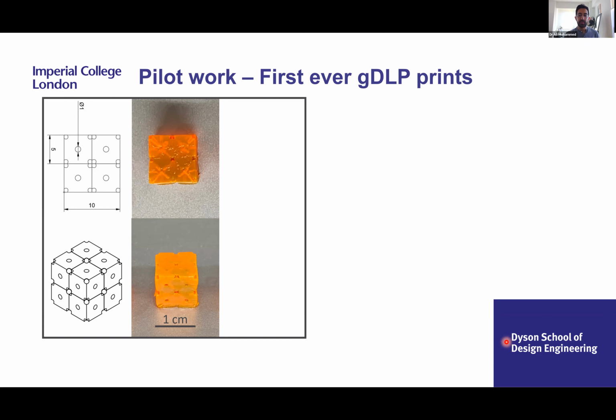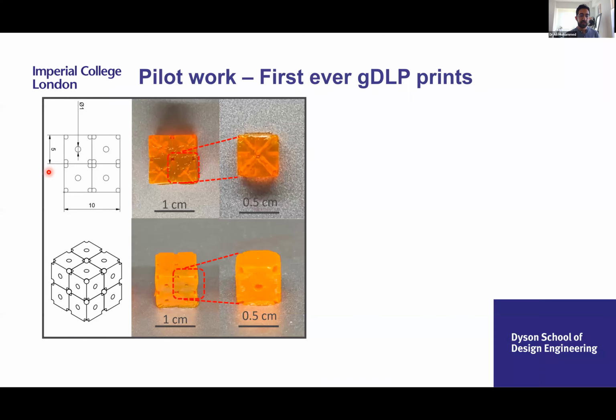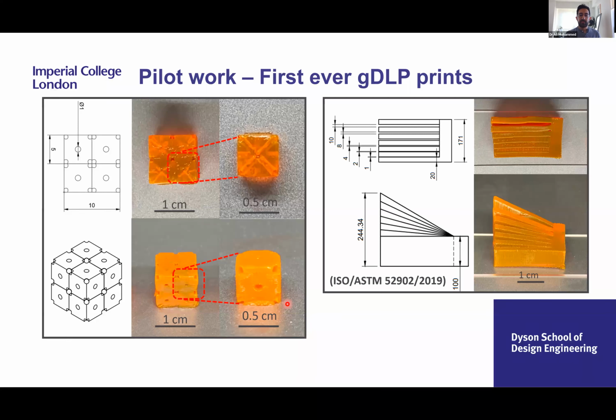So to further test our capability, instead of taking the entire lattice over here, we took 1 unit lattice. So this print is actually a quarter of the size of this entire one. This is 5 millimeters tall and wide, and the entire lattice structure is visible. And we can push these channels to 300 microns instead of 1,000 microns at the moment over here. So using some ISO standards from ASTM, we were also able to run some tests to see how accurate and how successful our materials can be at their soft state during the 3D printing process. And we saw that we can get up to above 95% accuracy on these prints.